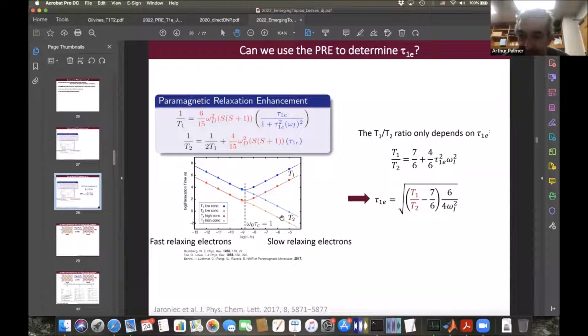If I could follow up on Lucio's first question, maybe you answered this earlier and I missed it, but you just said you can ignore spin diffusion. Why is that? Well, maybe not ignore, but the spin diffusion efficiency will depend on the strength of the interaction of the nuclei that we are looking at. So we tried to quantify how much the spin diffusion affects the overall buildup of the magnetization, and we did that just by looking at the buildup curves in a saturation recovery experiment, and we saw this markedly stretched exponential behavior.